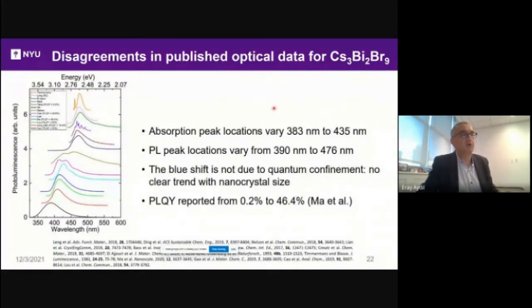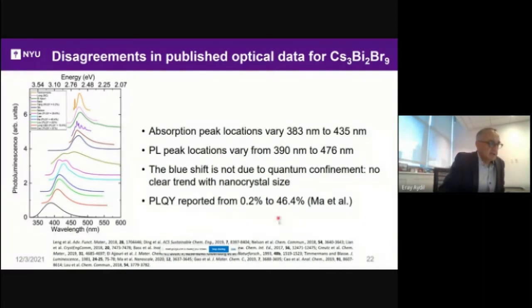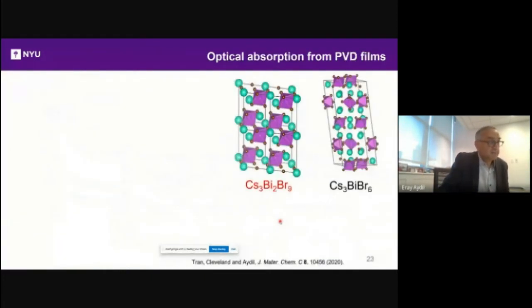And the same thing for photoluminescence. Photoluminescence peak is all over the place. PL peak locations vary from 390 to 476. And the blue shift, again, is not due to quantum confinement. And the photoluminescence quantum yield reported varies from 0.2 to 46.4%. People make a big deal out of this, that it's almost 50%, and you can make light-emitting diodes and things like that. There's a lot of that stuff in the literature.